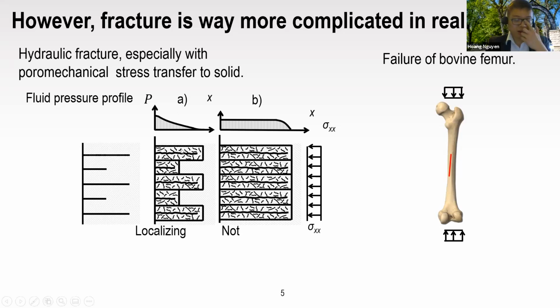However, when there's a crack, there's some release of the transversal stress and it creates a deviatoric condition. And under this condition, the breakdown pressure has been observed to be either higher or lower than it should be. So that also can be a scenario where the crack parallel stress comes into effect.